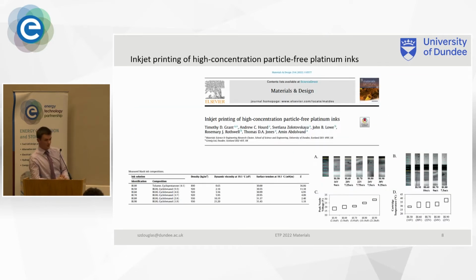So this ink was previously optimized by a previous PhD student. How he optimized it was by creating blank inks, which is the solvent without any platinum, that behaves the exact same way. So he created blank inks with different concentrations of a viscosity additive to change the viscosity of the ink, and then printed it and watched what ranges of nozzle voltages you could print within, and then the temperature at a single nozzle voltage to determine which concentration was the most optimum.